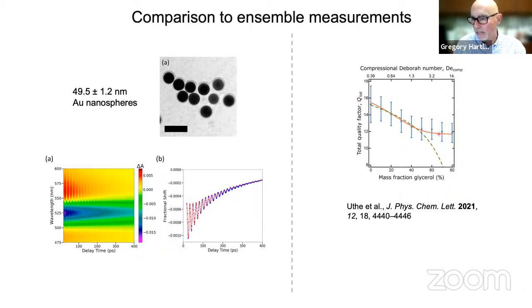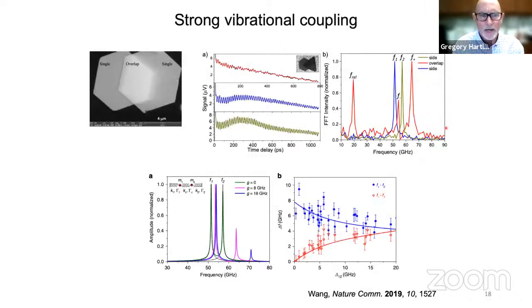So the blue markers here are the experimental measurements. The red line is the viscoelastic model of the liquid, and the green line is the Newtonian model, leaving out the relaxation time. You can see clearly, at high percentages of glycerol, an effect from viscoelasticity, like what we saw for the plates. Okay, so let me talk about 2 more things that you can do with the nanostructures if you have very high quality factors.